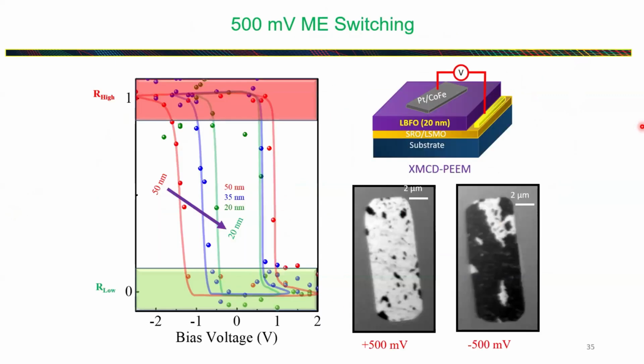Okay, then we have further demonstrated how one can reduce the thickness of your LBFO, which is a layer of BFO around 20 nanometer, and then what we have done here, we put platinum, cobalt iron, platinum, cobalt iron, which is around 2 nanometers here.